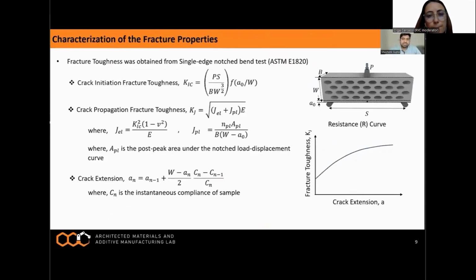The mechanical response was characterized by modulus of rupture and fracture toughness. The modulus of rupture was characterized using ASTM C78, and for fracture response, ASTM E1820 was used. In fracture, the compliance method was used for crack extension, and combined J-elastic and J-plastic terms have been used to calculate the fracture toughness as the crack propagates. We have also plotted the R-curve to show the resistance to crack growth in terms of the fracture toughness.